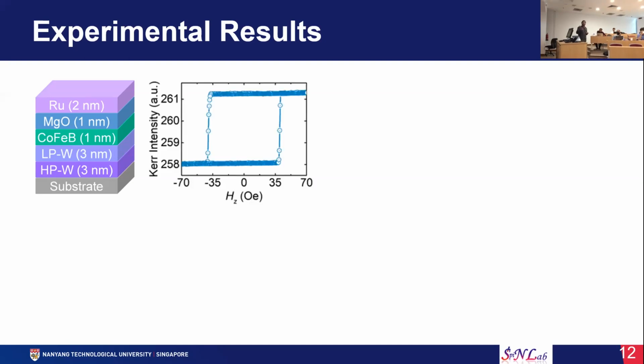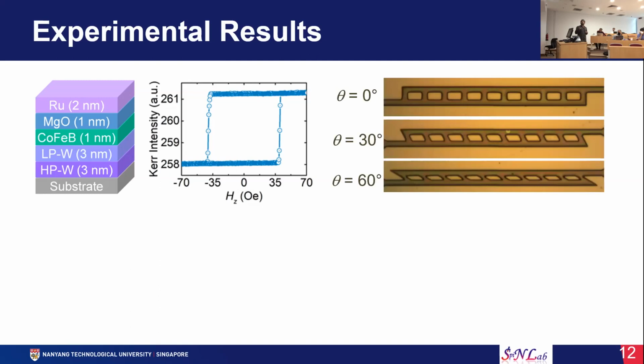In the magneto-optical Kerr effect measurement setup, we sweep the out of plane magnetic field and we get this type of Kerr signal. The squareness indicates the sample has perpendicular magnetic anisotropy and coercivity of around 40 oersted. The sample stack was deposited by DC magnetron sputtering, and from there, using optical lithography and ion milling techniques, we get this type of devices. These are the optical images of the devices.